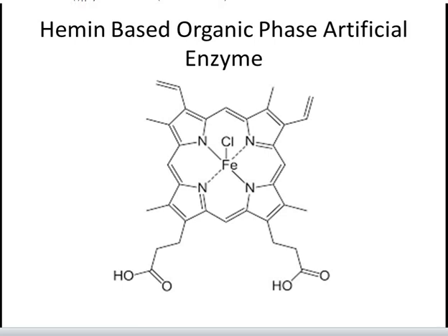Based on the newly discovered artificial enzyme formed by mixing hemin with supramolecular hydrogels via self-assembly of amphiphilic oligopeptides, a novel organic phase artificial enzyme electrode was made by coating the artificial enzyme on an electrode, which was then covered with sodium alginate for protection. Scanning electron micrographs showed that the supramolecular hydrogel kept its nanostructures on the electrode surface. Hemin dispersed in the supramolecular hydrogel as a monomer greatly promoted its direct electrochemistry behavior in organic solvents.